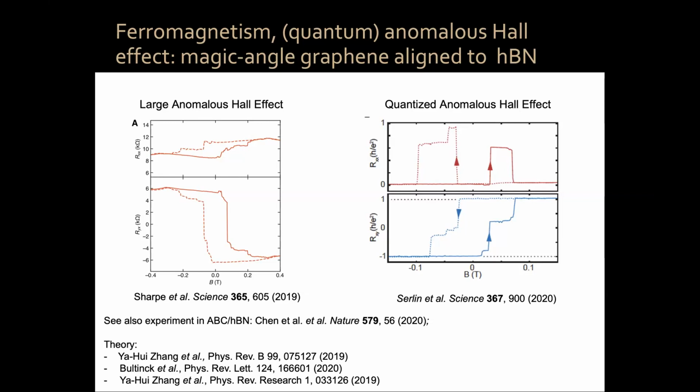We do not know. Now you have two pieces. You have the magic angle graphene, and you have to get that angle right. And then there seems to be an angle that you have to have with hBN to get this, which is not zero, because we've tried with zero many times and we didn't see it. I'll show you tomorrow what we found out instead. Several theories, Senthil, Allan MacDonald, etc., say that the graphene-hBN Moiré pattern is also 13 nanometers at 0 degrees. By chance it is the same as the magic angle one, but they're rotated with respect to each other. So if you want a matching of the Moiré patterns to maximize the symmetry breaking of the Moirés, you probably need something like 0.6 or 0.8 degrees between the graphene and the hBN. So now you have to get two angles right, the 1.1 and the 0.6 or 0.8.